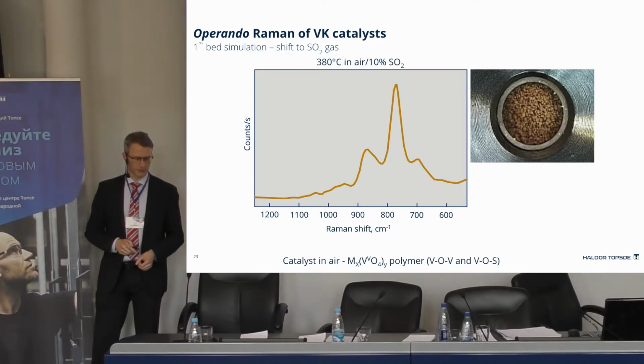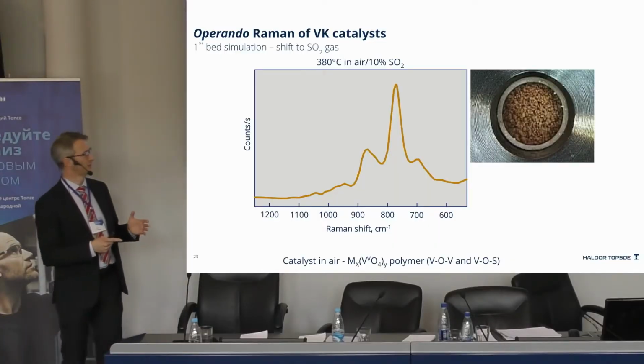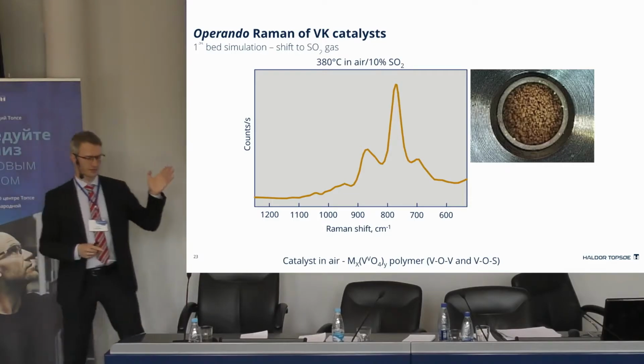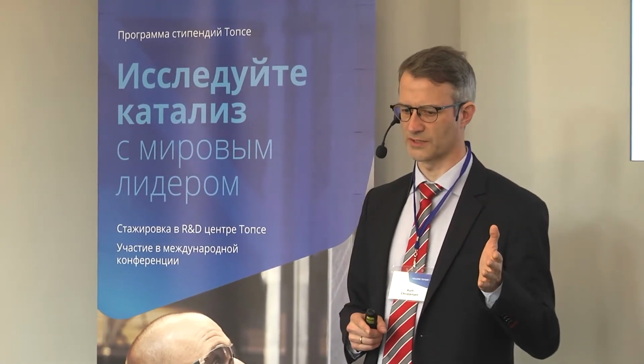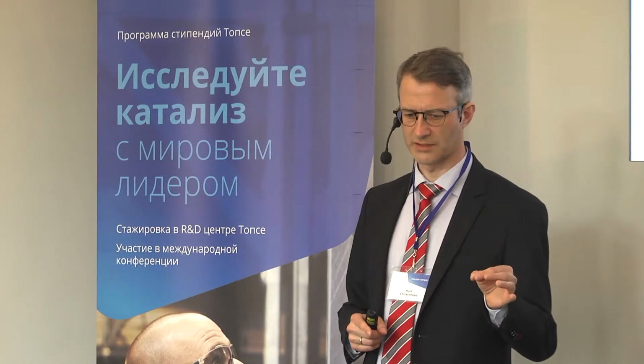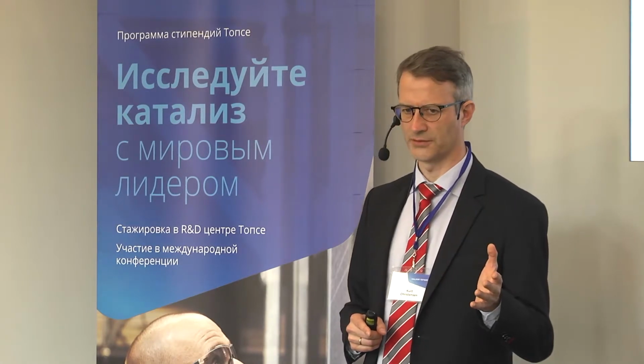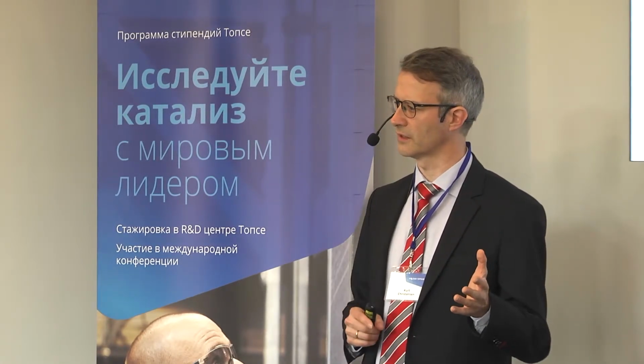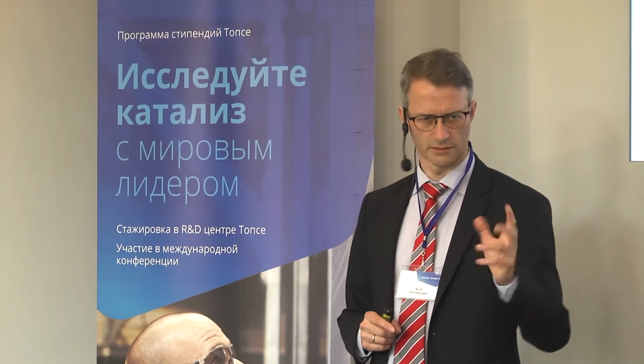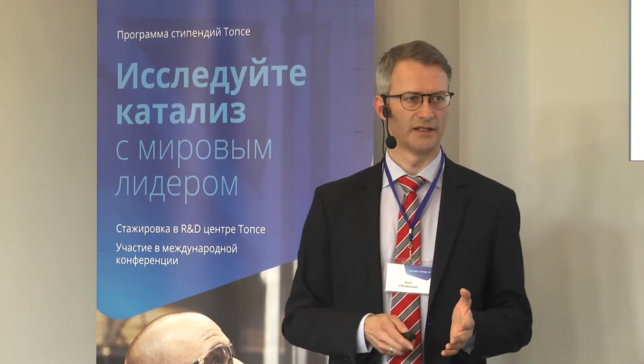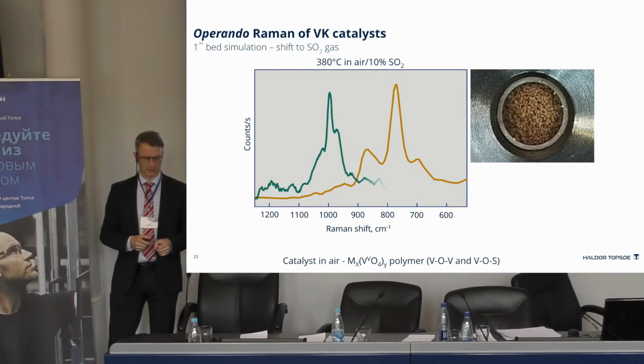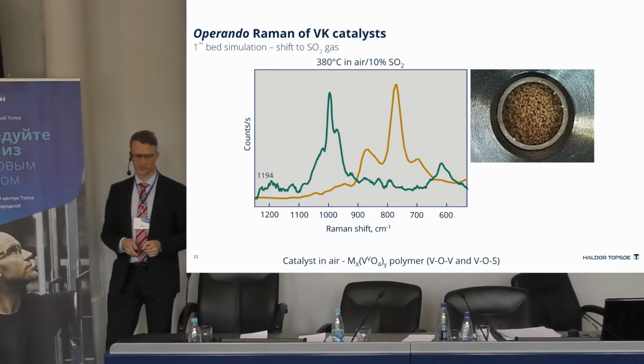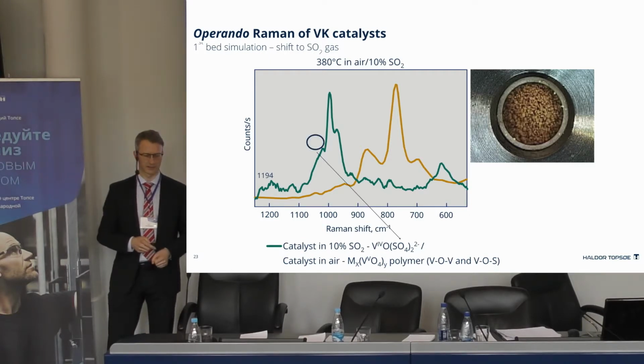Then let's try to run the reactor, and here you can see the catalyst is moving around, and after some time we will shift to the process gas, 10% SO2, 10% oxygen, and when that happens you can see it visually on the catalyst as well. Now it changes, the yellow disappears, and you are left with a gray-green color instead. This is quite obvious. When you put on a different gas, you get a different composition in one way. So let's see if the Raman agrees with that for this situation, and certainly you get a very different spectrum for the catalyst at this operating condition.